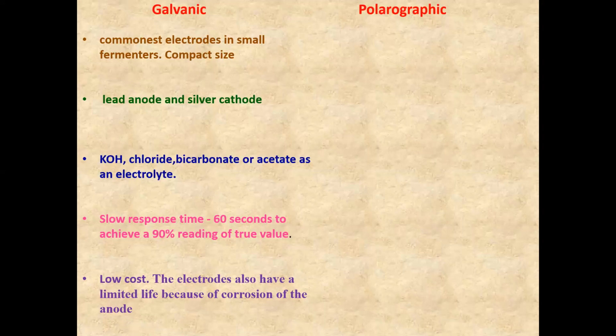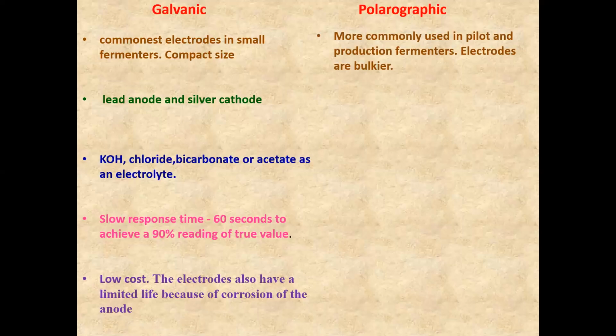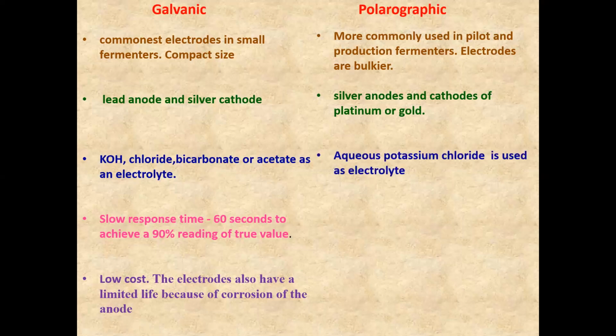Let's see the polarographic electrodes now. They are more commonly used in the pilot and industrial scale or production fermenters. They are bulkier than the galvanic electrodes, and they have silver anodes which are negatively polarized with respect to the reference cathodes of platinum or gold. So the cathode is made up of either platinum or gold, and aqueous potassium chloride is used as the electrolyte. Response time, see the difference. The response time is 0.05 to 15 seconds. So this is the advantage: as compared to the galvanic, the polarographic electrodes give you the reading in 0.05 to 15 seconds, and that also 95% of the true value.